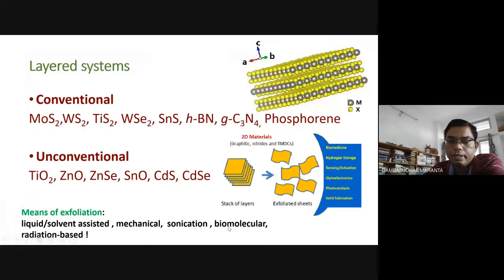Now, another interesting thing which is coming up, and people are trying to practice it, is biomolecular assisted exfoliation. For example, if you put a stacked material in collagen and leave it as it is, you do nothing, then slowly collagen will come and percolate through this spacing, breaking all these van der Waals bonds, and the layers will be separated from each other. The only problem is how to purify it, how to remove the unwanted products. That is an issue, but people are still following this new method, the biomolecular assisted method.